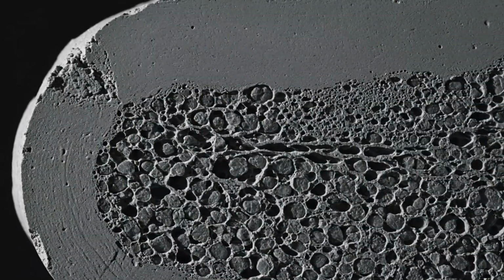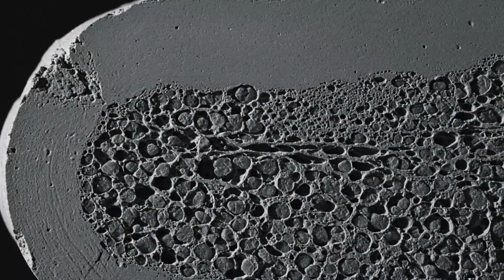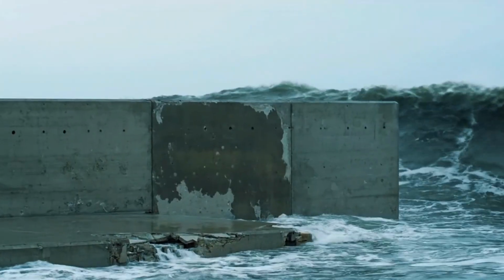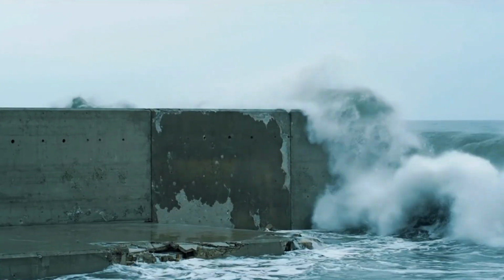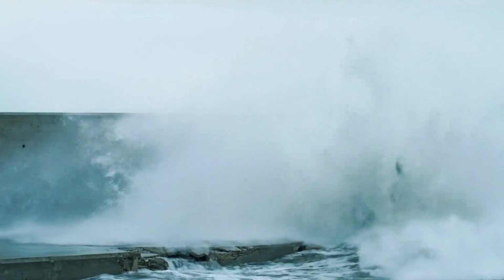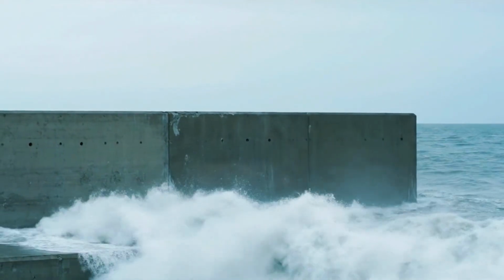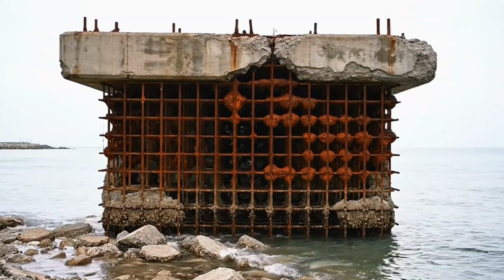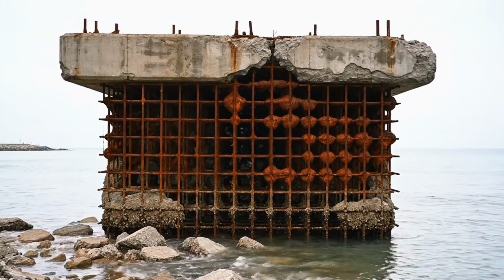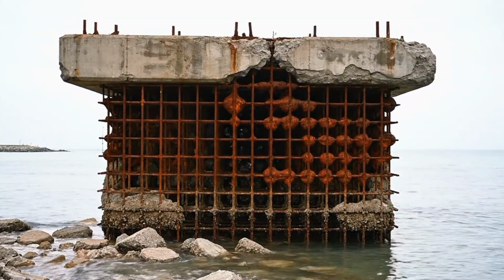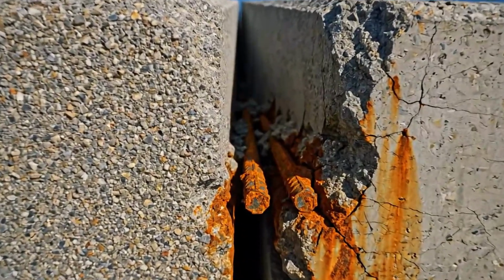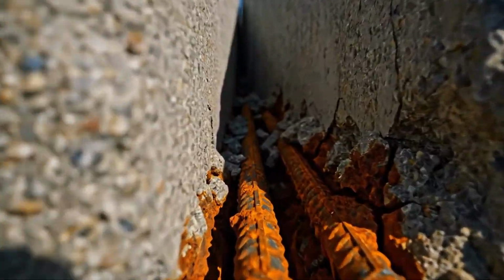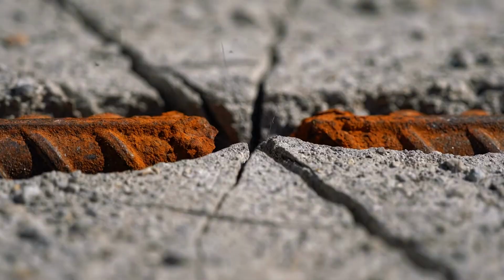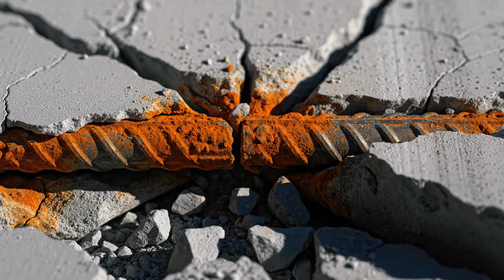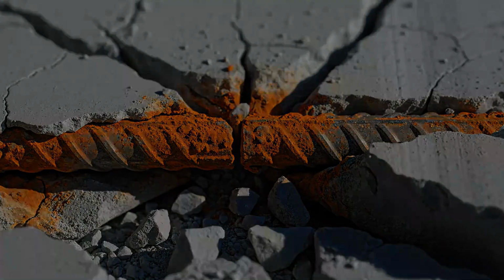But it has a critical weakness. It's vulnerable to chemical attack. In marine environments, seawater, saltwater spray, coastal exposure, modern concrete deteriorates through several processes. First, chloride ion penetration. Seawater contains chloride, which seeps into the concrete's porous structure. When it reaches the steel reinforcement bars inside, it causes corrosion. The steel expands as it rusts, cracking the concrete from within.